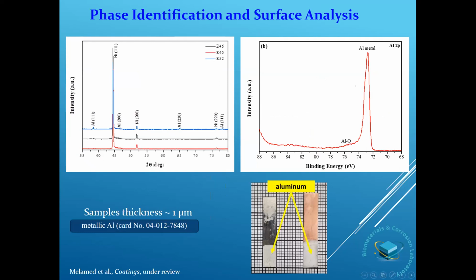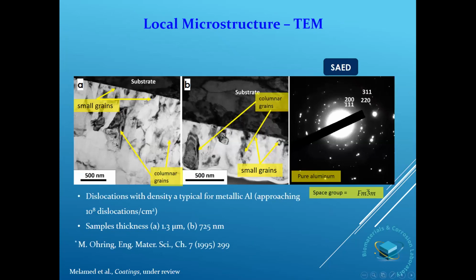The picture shows the macroscopic appearance of aluminum coatings on nickel and copper substrates. A grayish dense uniform coating with good surface coverage is evident in both cases. X-ray photoelectron spectroscopy indicated that indeed we get metallic aluminum. Several TEM samples, this was done in collaboration with Professor Louisa Meshi from Ben-Gurion University, were examined in order to assess the quality of the as-grown aluminum layers. We got typical selected area electron diffraction for aluminum. The dislocation density was also typical for aluminum.